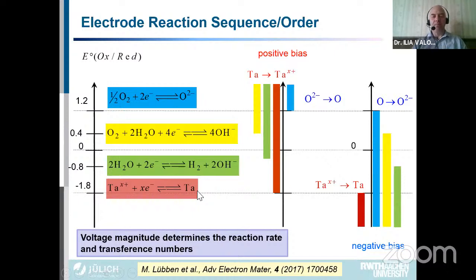And at the very end, when we apply very, very high negative voltages, we'll reduce tantalum ions to form tantalum metal. So this means that the voltage magnitude determines not only the reaction rate, because the higher the voltage, the higher the reaction rate, but it also lets us decide which voltage to apply in order to stop or accelerate one particular reaction. So this is an additional way of controlling the reactions.